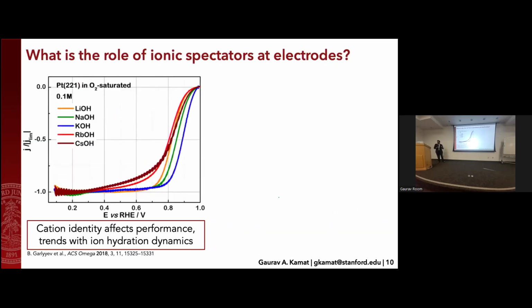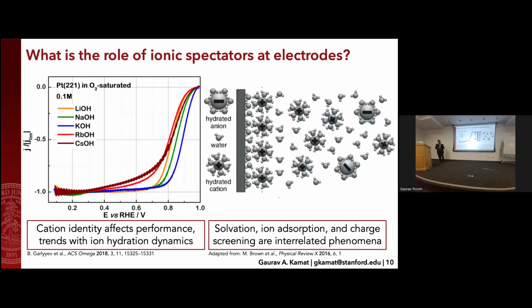So another thing I mentioned before, and it showed up in that picture, was ionic spectators. They're called spectators because they don't participate in the reaction just like oxygen does, which reacts away to form water or hydrogen peroxide. So lithium, sodium, potassium, rubidium, and cesium are just spectator ions that are not undergoing any changes, but you can see that they do have an effect that's based on the hydration dynamics of those ions. And that's because near the surface, you have these charged ions that have hydration shells. So you have ion adsorption, which is how these ions stick to the surface. You have solvation, and you also have charge screening, which is how charge emanates from these ions and from the electrode, and how those things interact in the double layer microenvironment. And all of these affect what's going on near the surface.